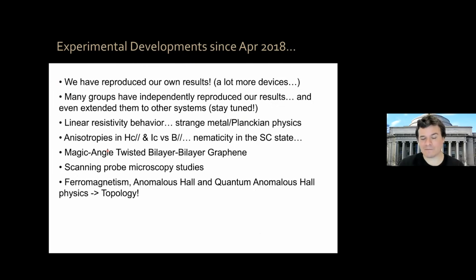Now, since then, we have learned a lot about the properties of this system, okay? The system has a linear in temperature resistivity behavior, which is very reminiscent of the strange metal physics in correlated systems with Planckian dissipation. It also exhibits anisotropies in, for example, the critical parallel magnetic field, okay, which indicates that the superconducting state is nematic. That means it breaks lattice rotational symmetry, for those of you that know this.